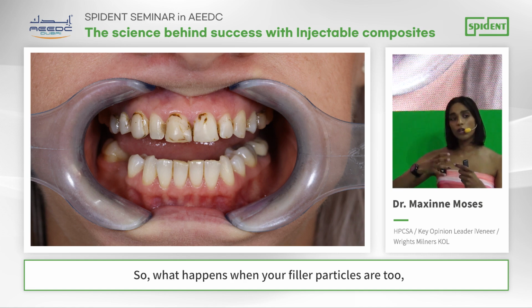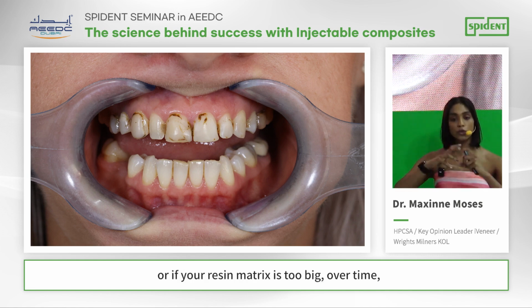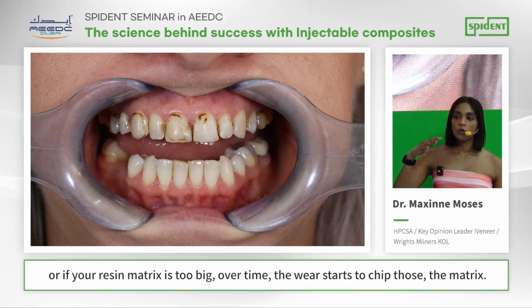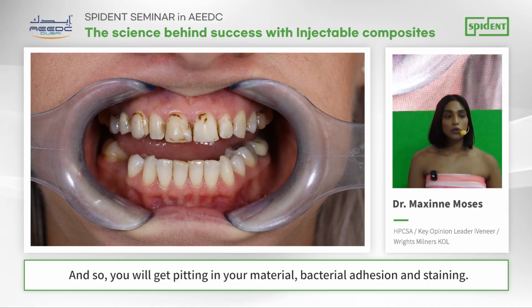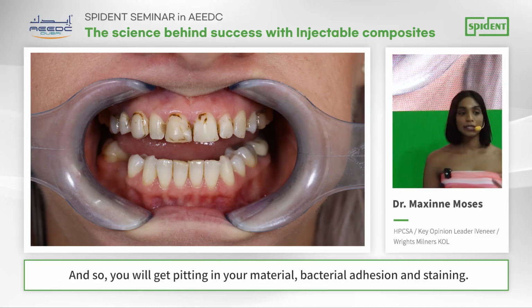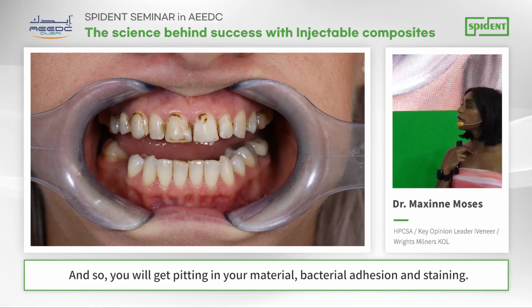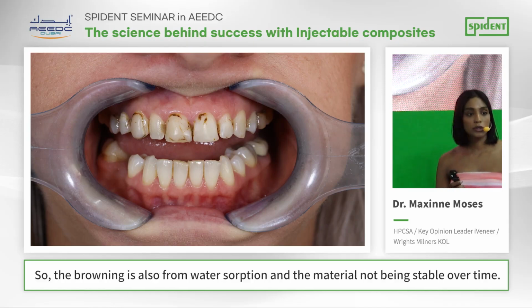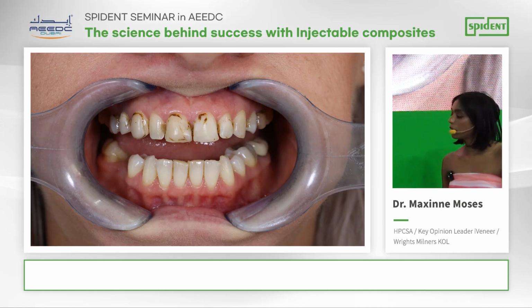What happens when the filler particles in your resin matrix are too big is that over time the wear starts to chip the matrix. And so you will get pitting in your material, bacterial adhesion, and staining. The browning is also from water sorption and the material not being stable over time.